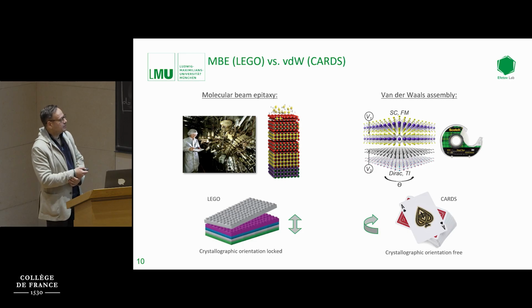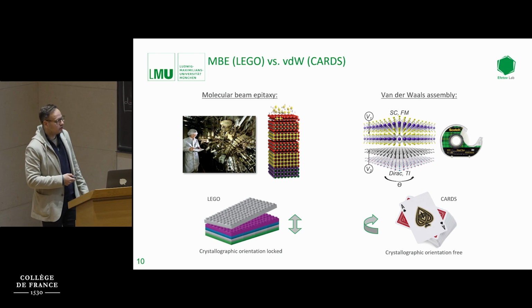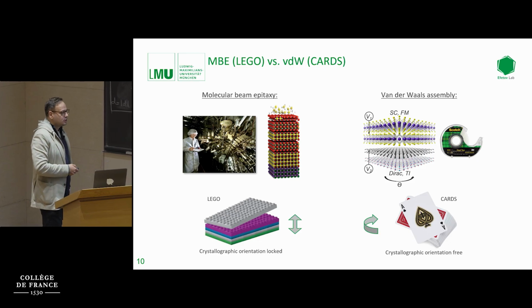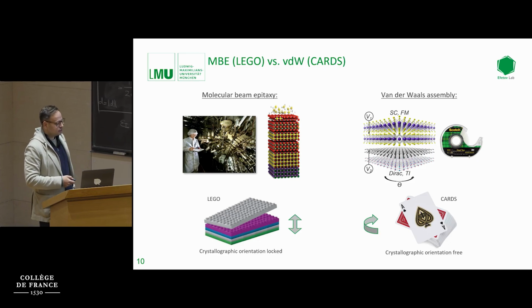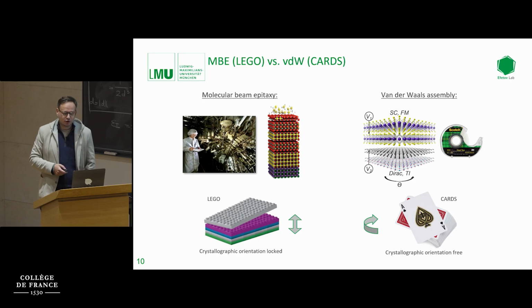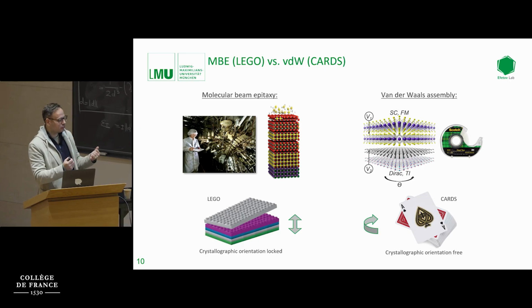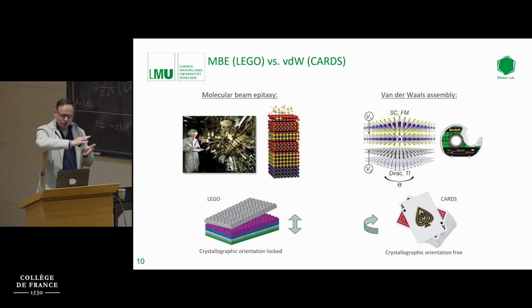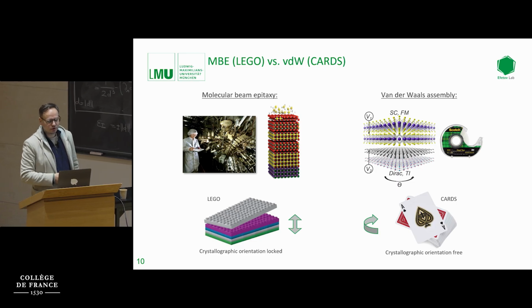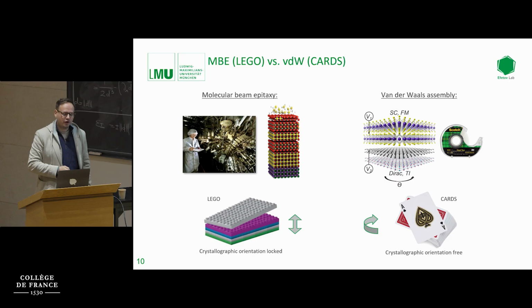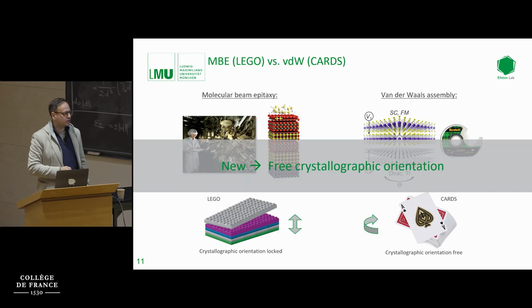And of course, you can switch up the material species that you wanted. But this type of assembly, which starts with single atoms, resulted in the assembled layers inheriting the crystallographic orientation of the underlying material they were grown on. Here in van der Waals materials, because we start not with atoms but with crystals, each 2-dimensional layer is already like a preformed crystal. We really have the freedom to twist and rotate them and very precisely create these superpotentials that form the Moiré superlattice.